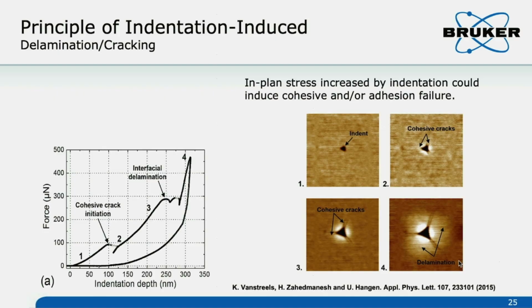Okay, not only for the film thickness, for the thin film, a lot of people are also concerned about the film delamination, film fracture toughness. This is a very important topic. We already showed the example in my previous presentation about the pop-in. So this is from the paper. You can see when we are doing the indent, this is the normal indentation. When you see the pop-in, you see the cracking. So you can get this from SEM or from our SPM image.